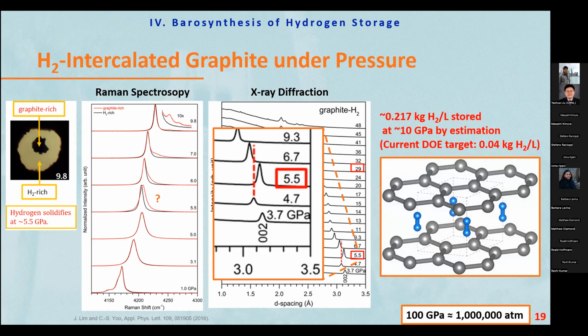When you estimate how much hydrogen is stored in the graphite, this is simply the figure with the carbon rings in the graphitic layer positioned with one hydrogen molecule. When you calculate this at 10 GPa, the amount of hydrogen would be 0.2 kilogram per liter. And the current DOE target for hydrogen storage for energy application is 0.04 kilogram of hydrogen per liter. So it's around 5 times better than the DOE target, but it's 10 GPa. That's the problem. But this opens the way to use graphite as the hydrogen storage.